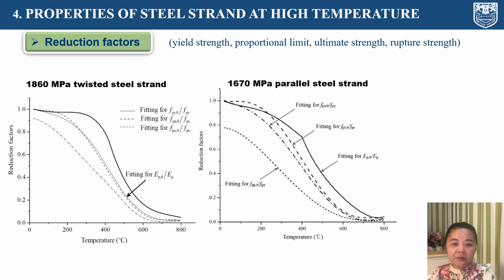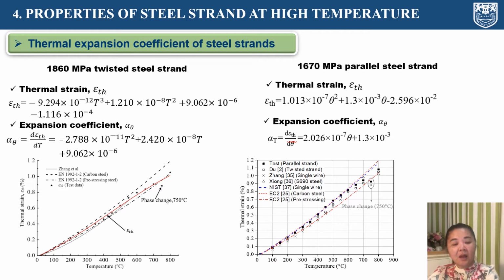The reduction factors of the effective yield strength, proportion limit, elastic modulus, and ultimate strength for 1,860 MPa twisted strand are fitted to test data well, as shown in the figures, as well as 1,670 MPa parallel strand. The formulas of thermal strain and expansion coefficient dependent on temperature are determined from regression analysis on the test data for twisted strand and parallel strand respectively, as above.